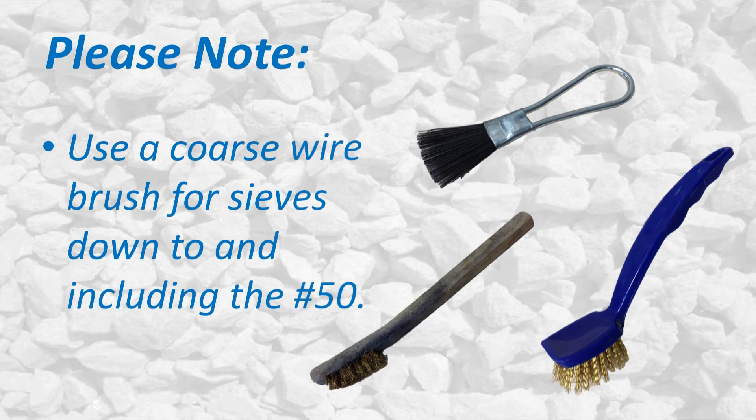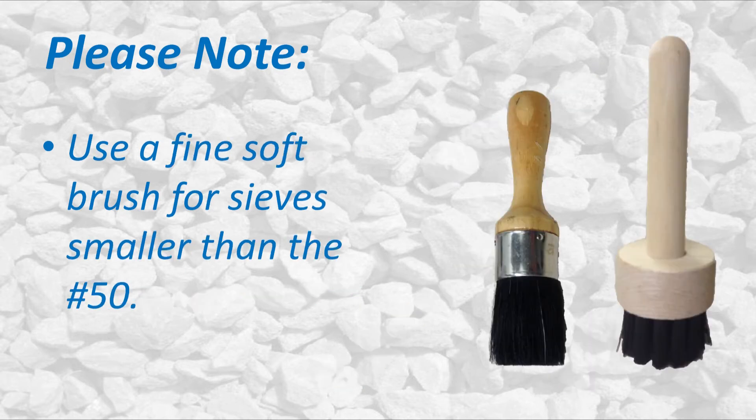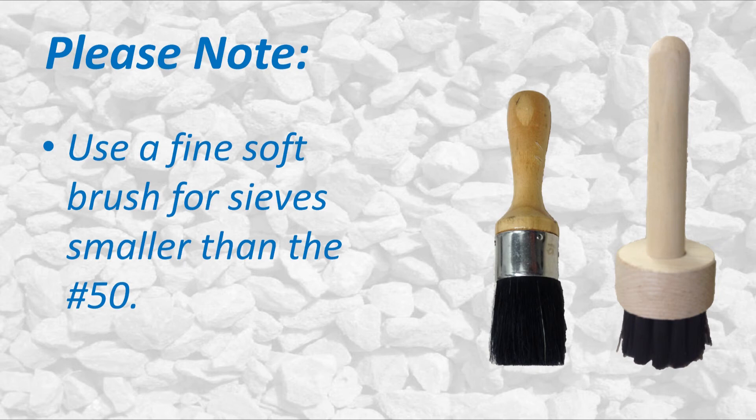As a general rule, use coarse wire brushes to clean the sieves down through the No. 50 sieve. Any sieve with an opening size smaller than the No. 50 should be cleaned with a softer cloth hair brush.